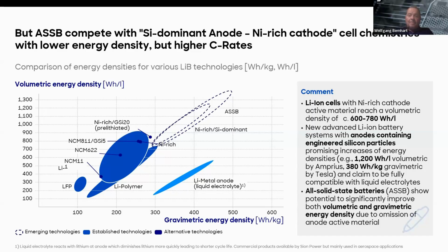So what we see is that lithium-ion cells with nickel-rich cathode active material can already achieve a relatively high energy density in terms of volumetric energy density. And those systems where the anodes contain engineered silicon particles already allow promising increases of energy density. Just a few examples: Amprius, for example, claims to reach up to 1,200 watt-hours per liter. And we do see high gravimetric energy density as well, fully compatible with liquid electrolytes. But all solid-state batteries show the potential to significantly improve both the volumetric and the gravimetric energy density due to the omission of anode active material.